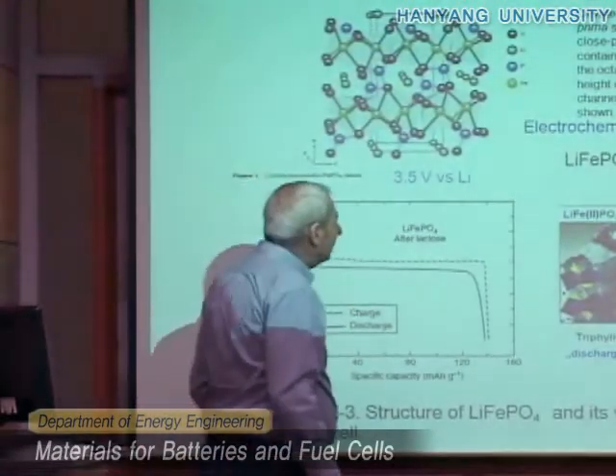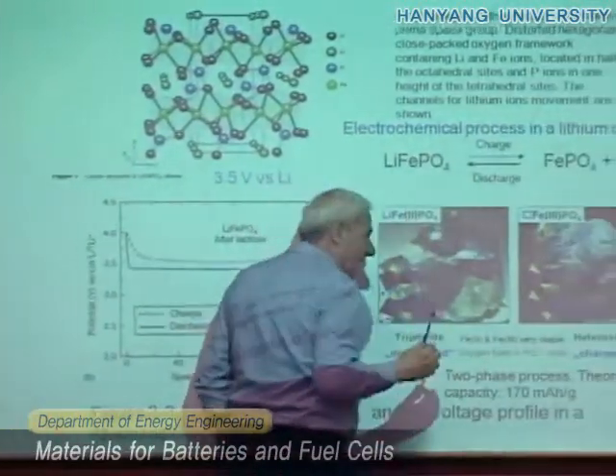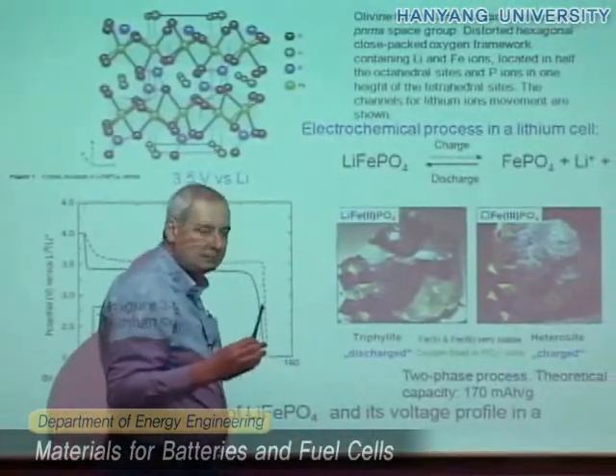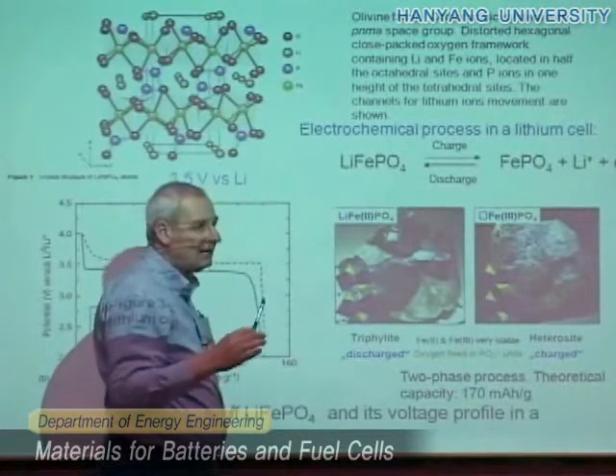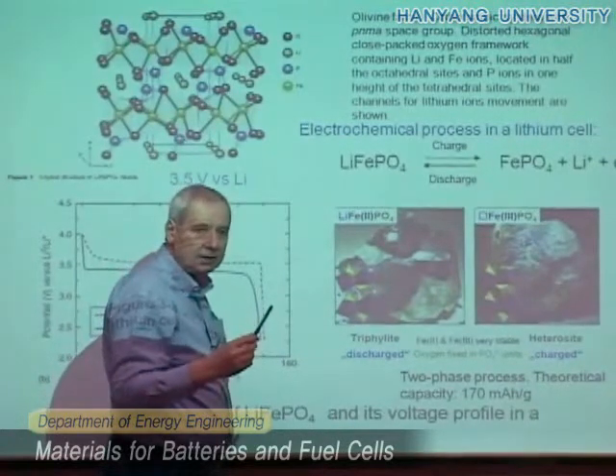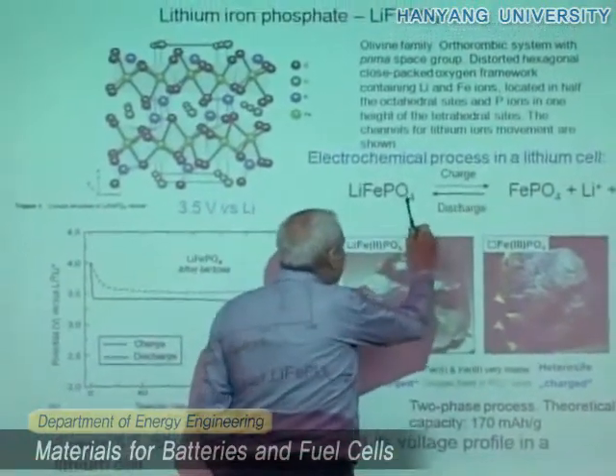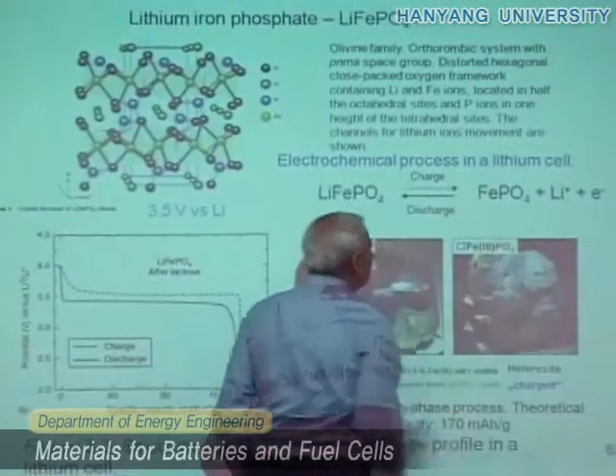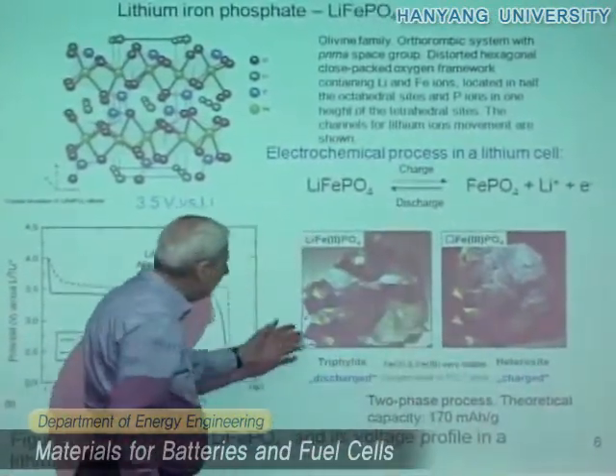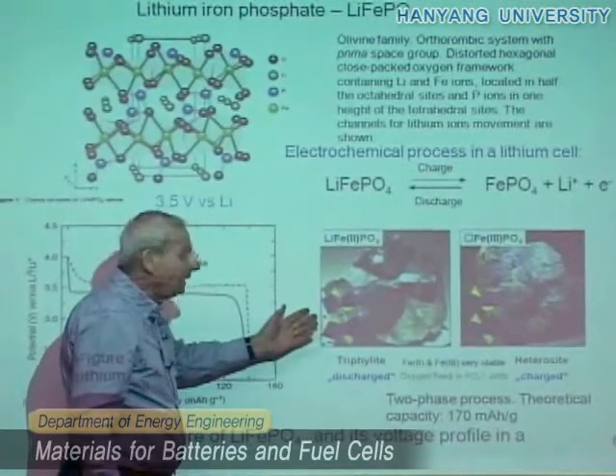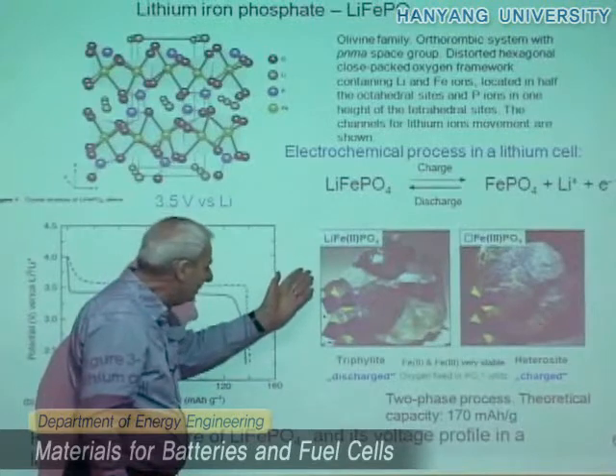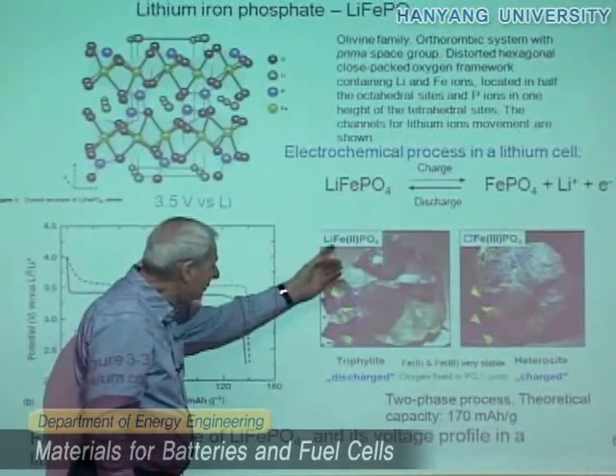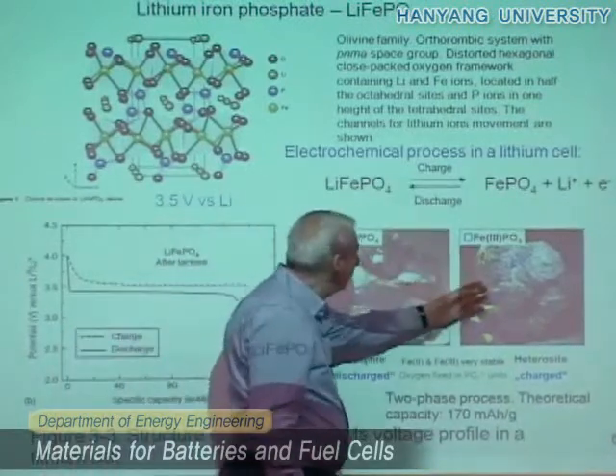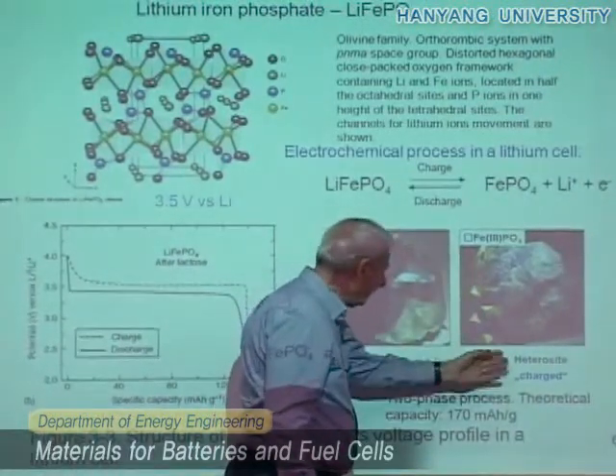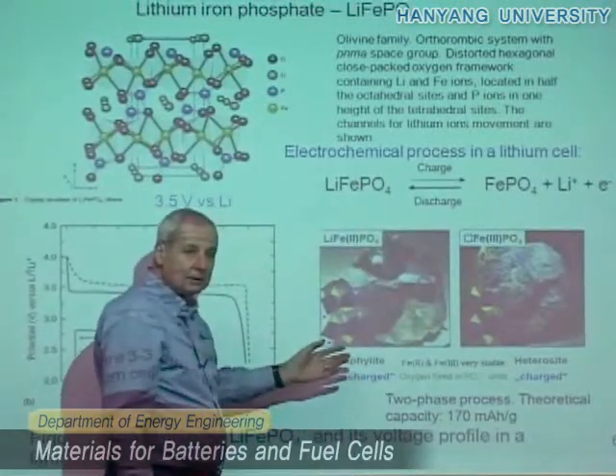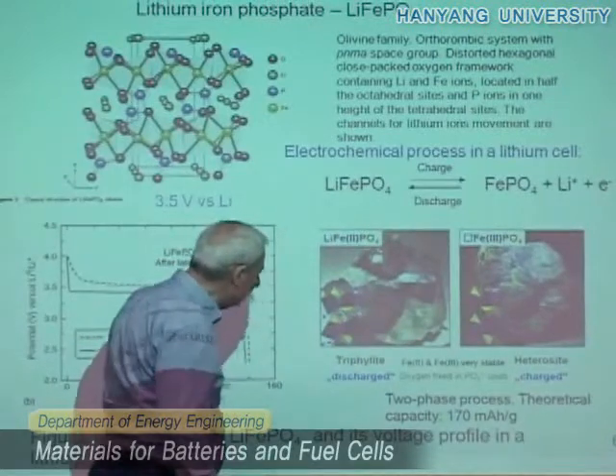What is the electrochemical process here? Again, remember that we are talking about cathodes. All the cathodes have to be able to give lithium. Okay? So here, lithium is removed all the way to form this compound. And then it can go back. And you see that in this way, we actually pass from one phase which is called triphylite, which is this, to the other phase, which is called heterosite. So both of them occur in nature. You see some pictures here.